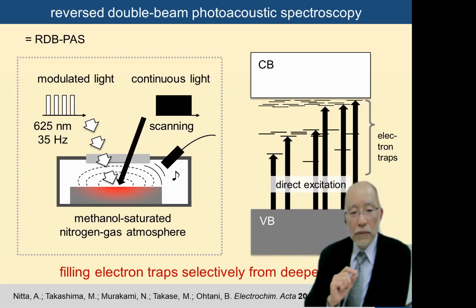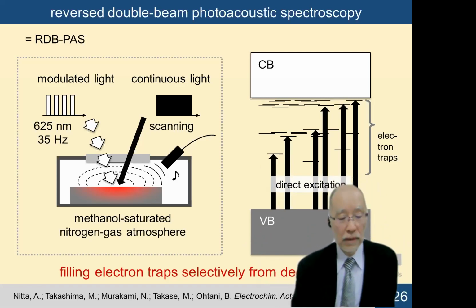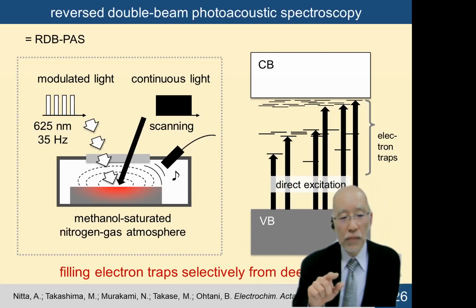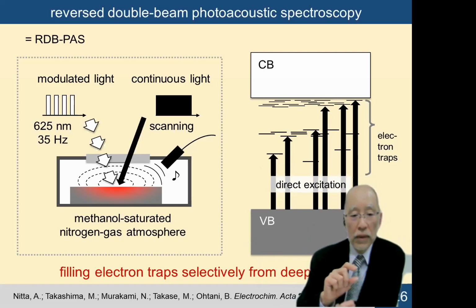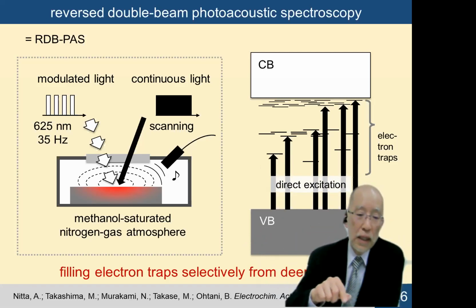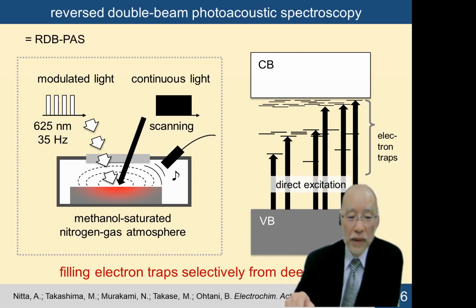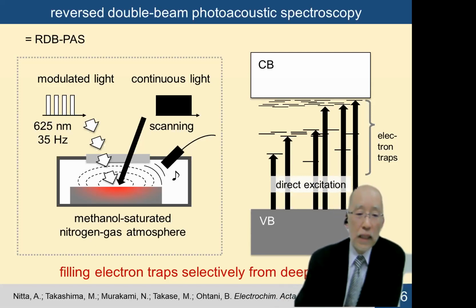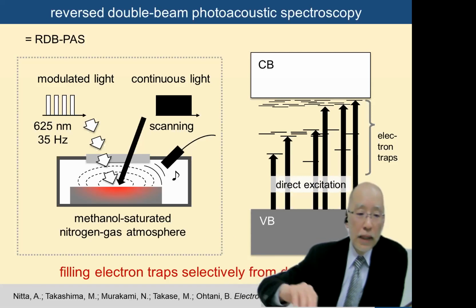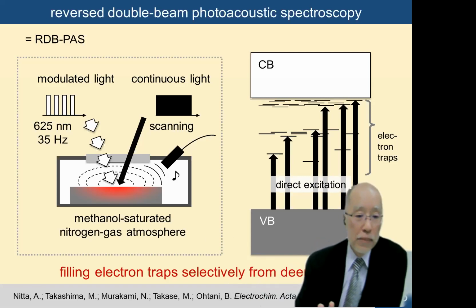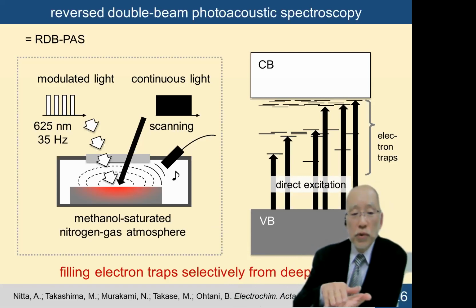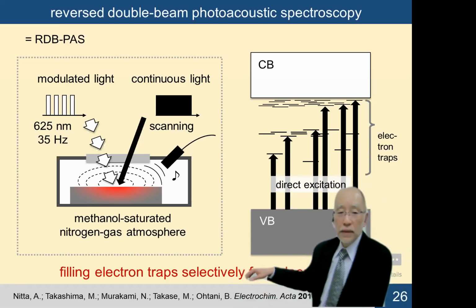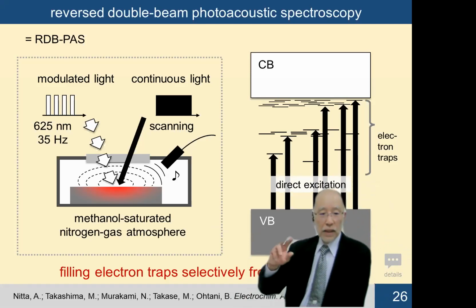So for example, titanium oxide can be reduced by hydrogen, and that produces Ti3+. That is, one electron is injected into Ti4+ cation and it becomes Ti3+. And probably you know that this Ti3+ containing titanium oxide turns blue or blue-gray. So that means red light is absorbed by this, so a new absorption in the visible region appears.